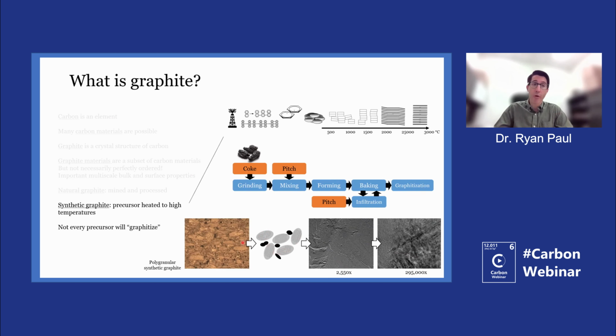But it's very hierarchical and very heterogeneous in its form, in that there are cracks and pores at different length scales that are very important for the final application and final properties. But even as you zoom in to very high magnification, you can see it's not just this sort of cartoonish, long range order of perfect planes extending in all directions, but there's grain boundaries, there's these hierarchical pores and cracks, there's a polygranular nature. So a really diverse set of structures that can be formed from a synthetic, manufactured graphite process. So everything in between is very important for different applications.